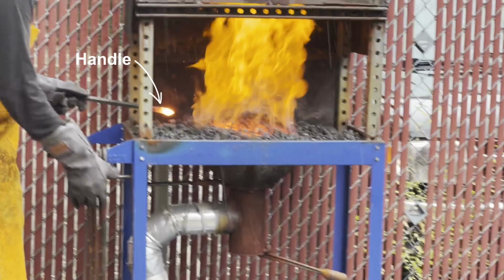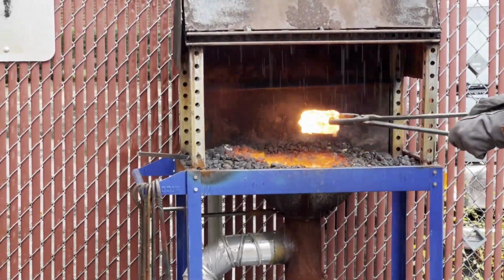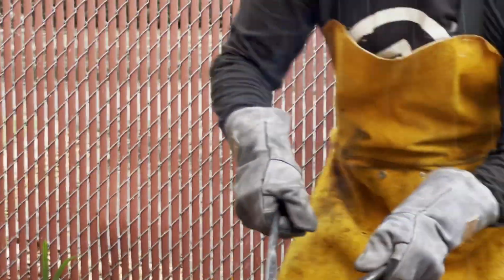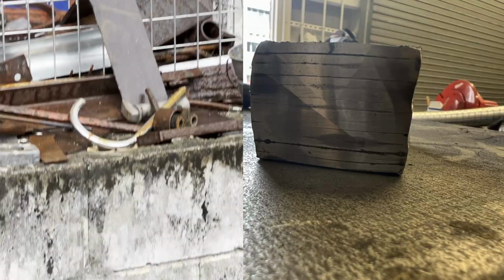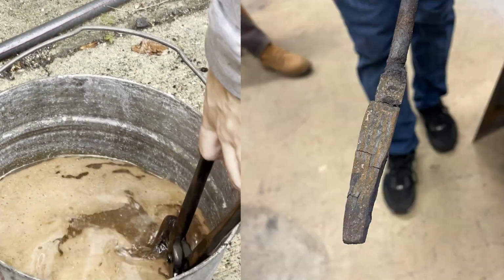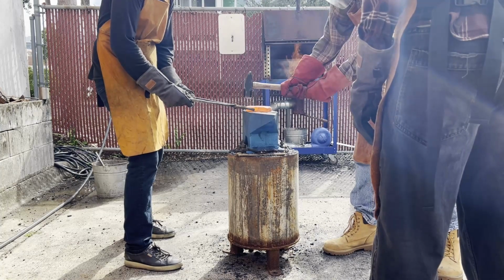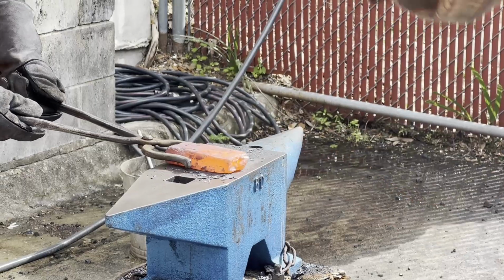Unfortunately, the temporary handle proved more temporary than expected. We believe the billet overheated while we tried recovering it with tongs, partially causing some delamination. We tried to cut off the affected plates and carry on, but the billet cracked during forging a few days later. We restarted with a new billet, this time fully welding the sides to prevent oxide formation between the plates. This forge welding attempt succeeded, and we were able to begin forging the blade itself.